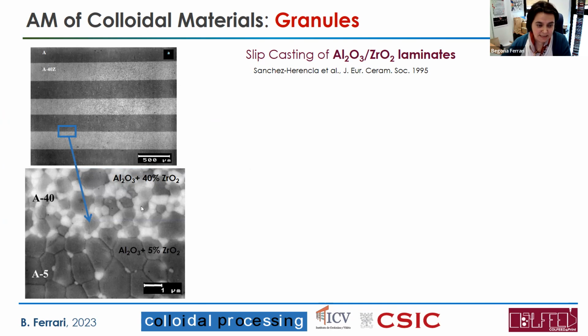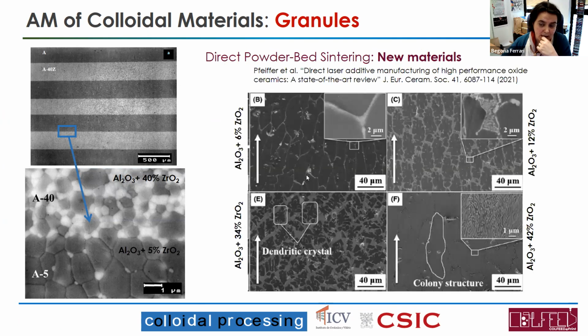create new material. You can see here in this micrograph a mixture between alumina and 40% of zirconia, and you can process it by slip casting and also after sintering, right, in a regular treatment. And here you can see this same composition, the microstructure you achieve when you use a laser sintering, right? This kind of direct powder bed sintering technology, right? So in this kind of additive manufacturing, we are creating new materials to study, right?